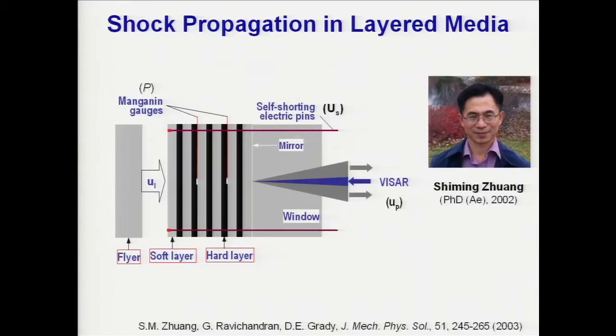So we were interested in this sort of concept, but at a more fundamental level. So here we are going to look at one-dimensional impact of layered media. Once again, similar to the idea of bulletproof glass, we have a soft layer and a hard layer. And here we also measure the stresses inside this layered media using manganin gauges. And once again, we are measuring the particle velocity at the rear surface and also the shockwave speed arrival. This is the work of my former student, Shiming Zhuang.